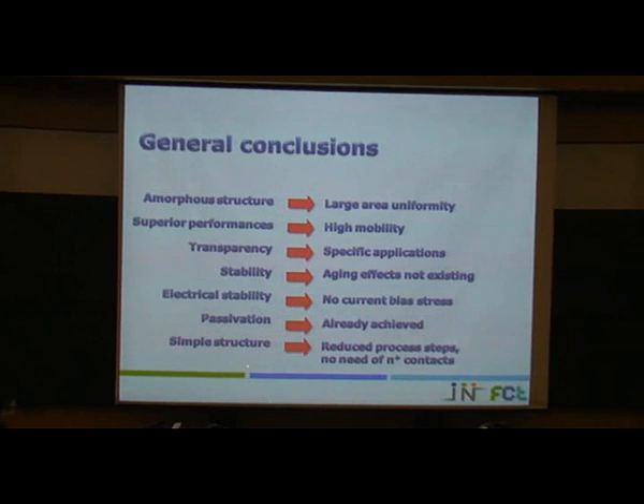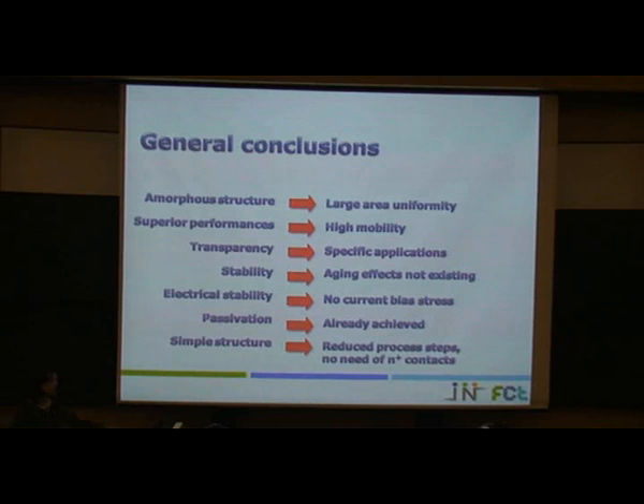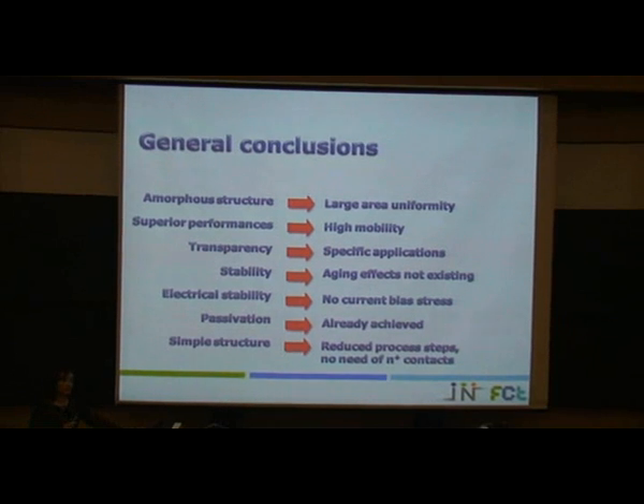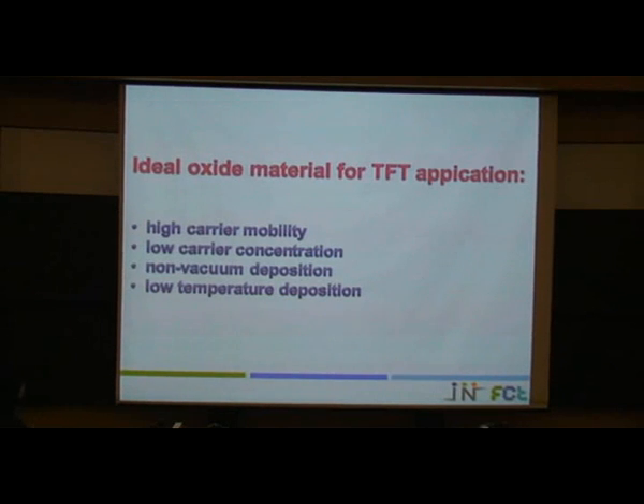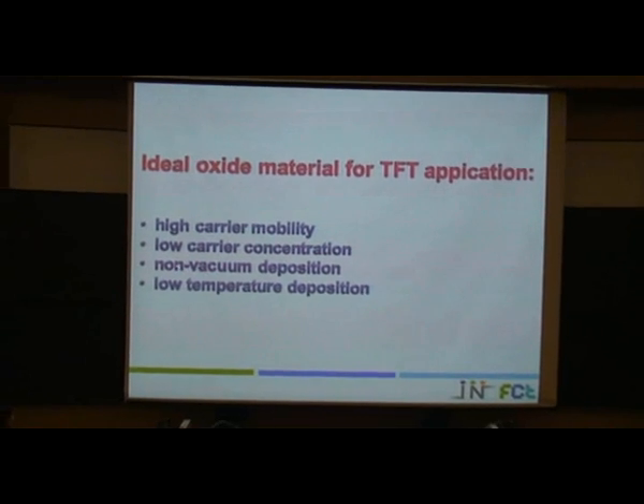And also the structure is simple because we don't need to use the N+ contacts as in the case of the MOSFETs or as in the case of the amorphous silicon TFTs. The amorphous silicon TFTs need to have an N+ contact. So this is what we are looking for, the ideal oxide material for TFT application. This material should have a high carrier mobility, a low carrier concentration, a non-vacuum deposition, if possible, and also low temperature deposition. So this is our ideal semiconductor.